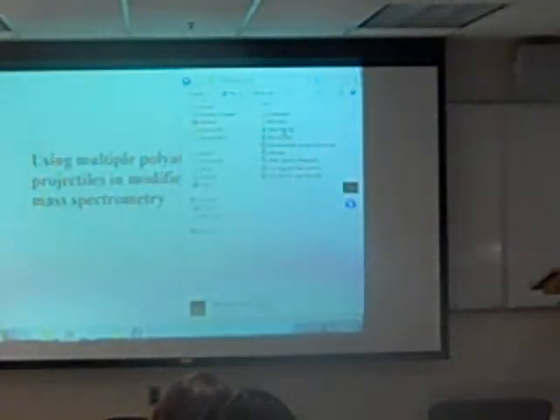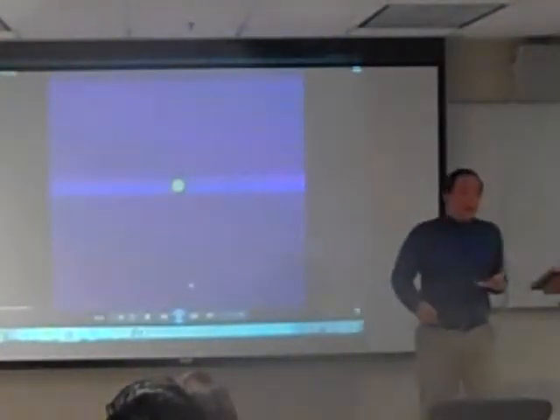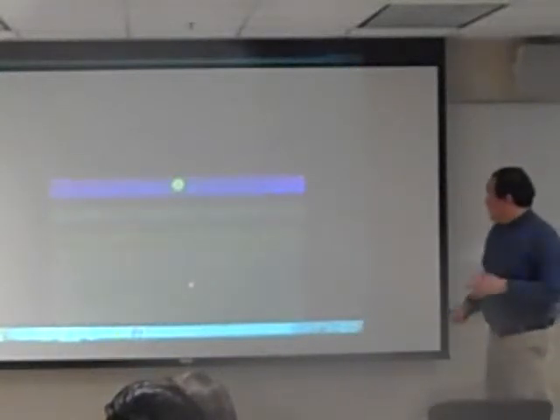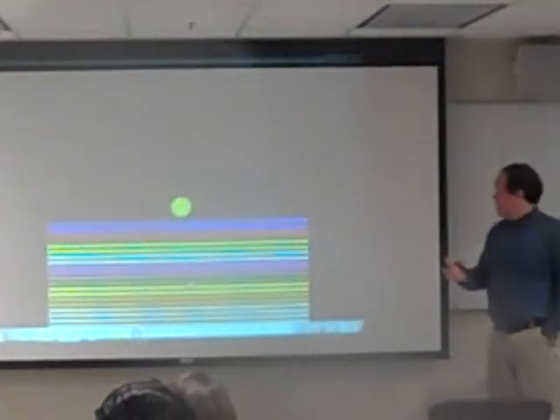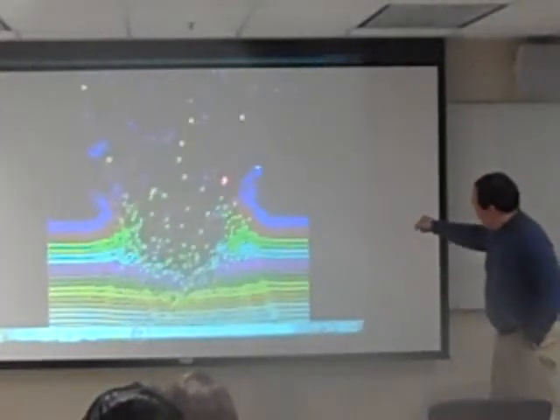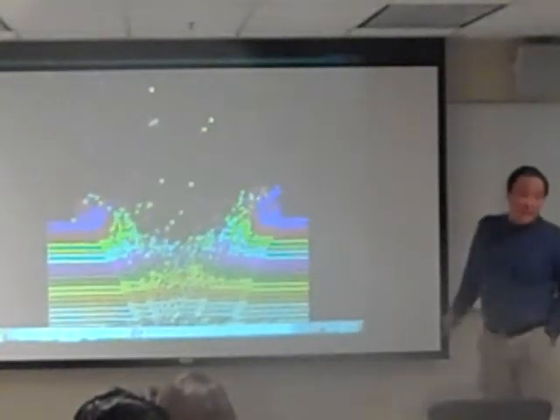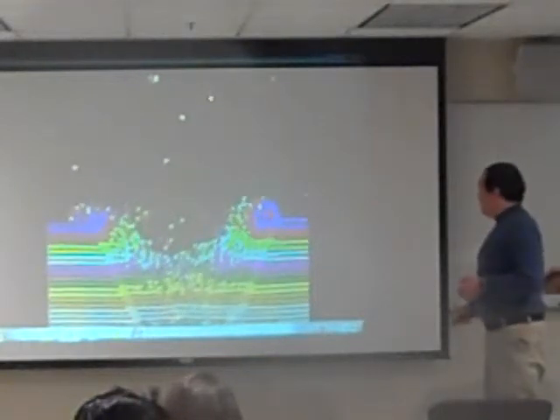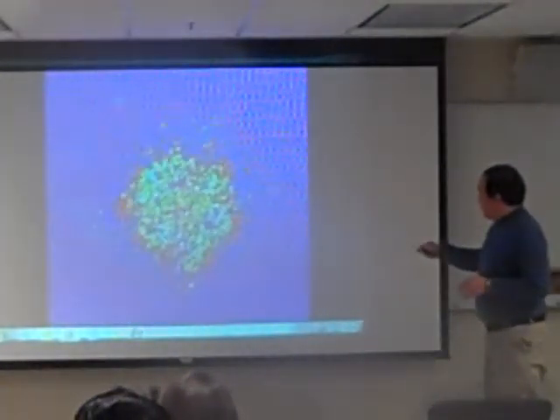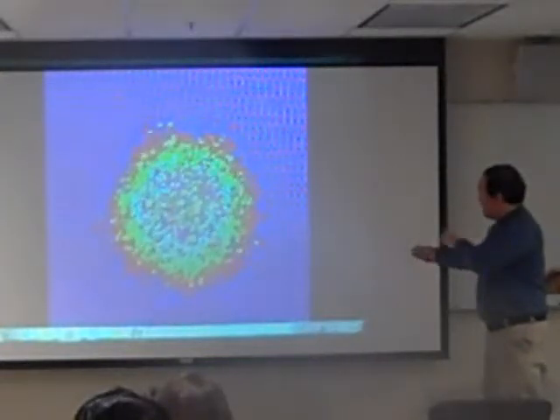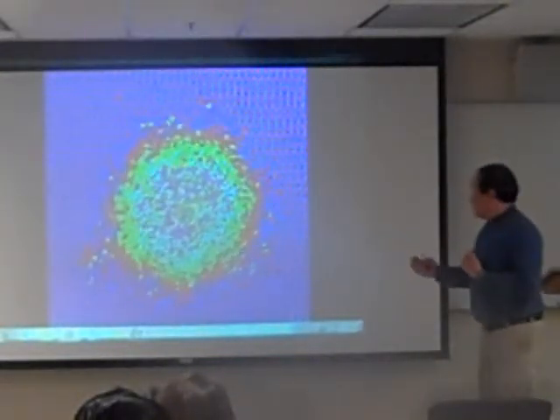You can see that the surface is disturbed, but very little of the secondary ions is produced in that fashion. Now, if we did the same thing, but looked at a heavier atom, let's say we used Buckminster fullerenes. It's a heavier projectile, but interestingly, it causes less surface damage and maximum secondary ion use. So you see there's a lot of secondary ion use, but if you look at the lowermost surface, this remains relatively undamaged as compared to the gallium. And this is the top view here. You can see the secondary ions that emerge from that substrate.